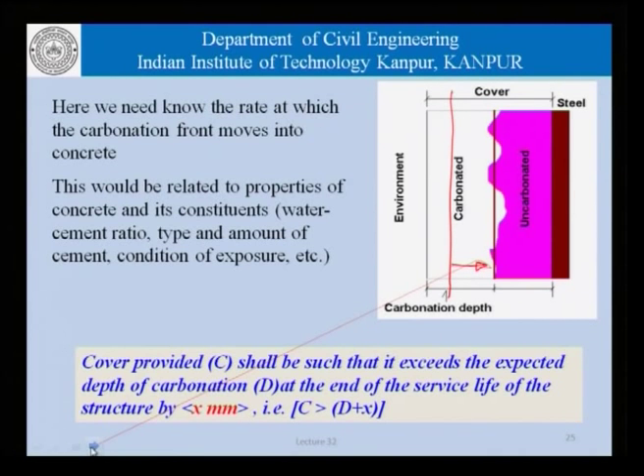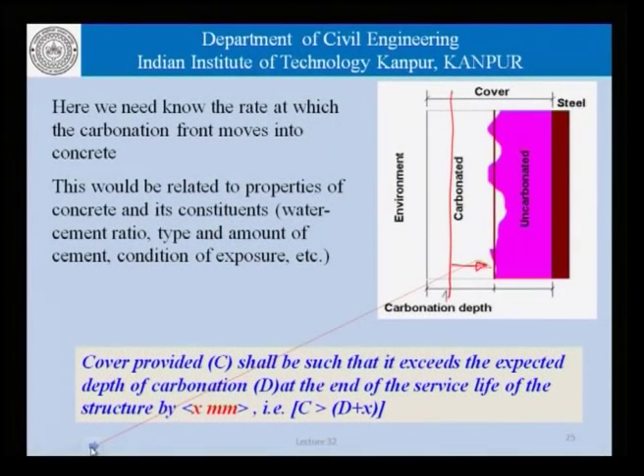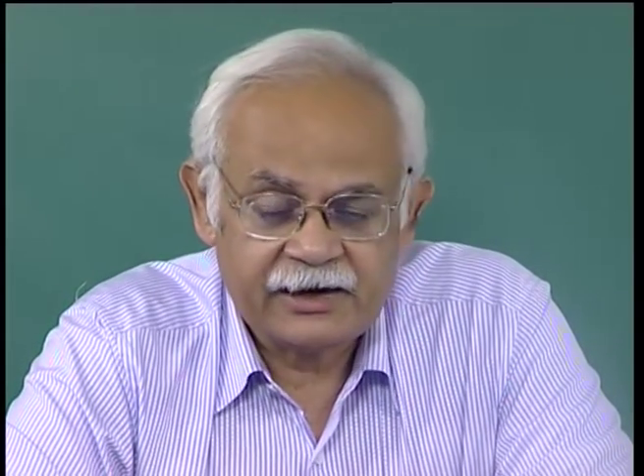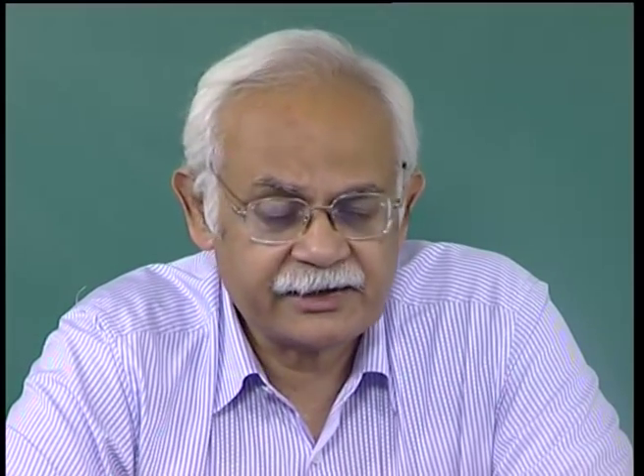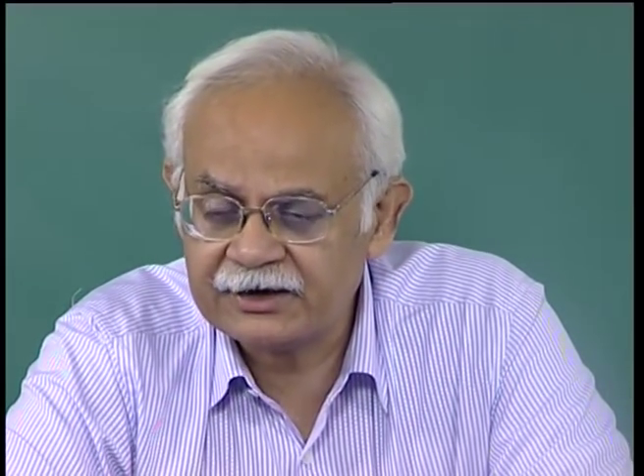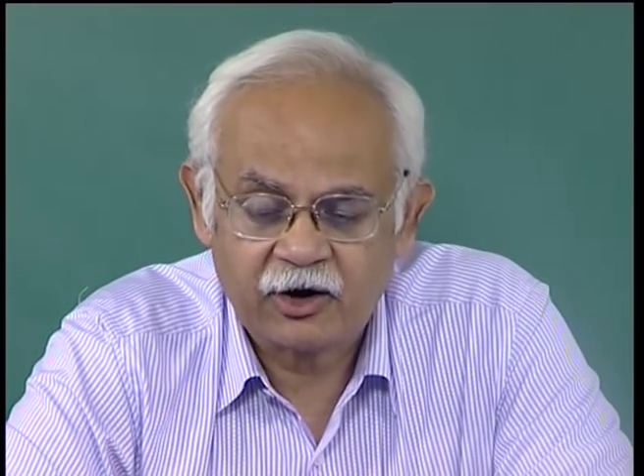And indeed, the rate of movement of the carbonation front into concrete would be related to properties of the concrete and its constituents, for example, the water cement ratio, the type and amount of cement, the conditions of exposure. Conditions of exposure are important in terms of, for example, whether the concrete is indoor or outdoor, because if it is indoor it is not subjected to rain, if it is outdoor it is subjected to rain. Rain tends to make the concrete wet, and in wet concrete carbonation progresses at a different rate than it progresses in the dry concrete. So, all these factors have to be borne in mind when we are talking in terms of how quickly or how slowly will the carbonation front move into the concrete through the cover concrete.